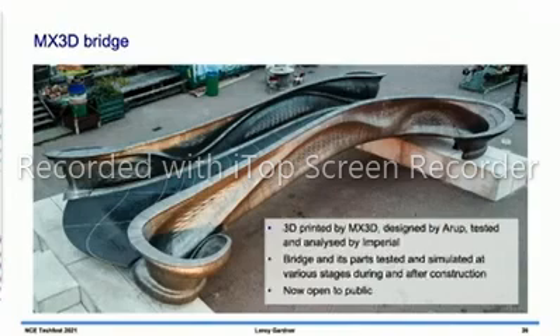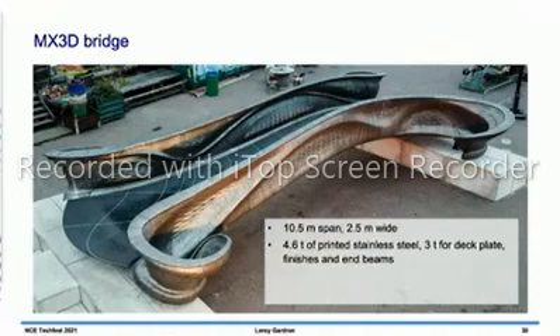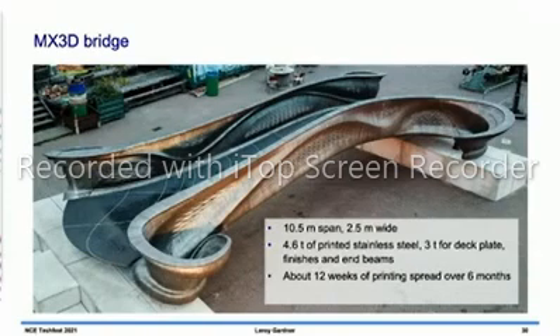It's 10.5 meters in span, about 2.5 meters wide. It's 4.6 tons of printed stainless steel, and that's all of the structural elements of the bridge. And then there's about 3 tons of deck plate and finishes and end beams in conventional stainless steel. There was about 12 weeks of printing, and that was spread over a 6-month period. And the handrails of the bridge are 3.5 millimeters thick, and the substructure is 8 millimeters thick.